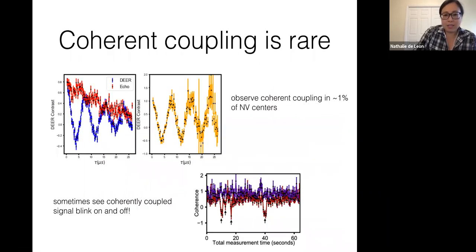Okay, the last statistical puzzle is that coherent coupling is actually quite rare across all of these observations. If you really had this low of a density, you should basically see a strongly coupled surface spin the vast majority of the time. But looking over our historical data sets and the Lukin group's historical data sets, you really only observe coherent coupling, which looks like this, where you have these oscillations because you're transferring polarization back and forth between the NV center and the surface spin. We only observe this in maybe 1% or a few percent of NV centers.